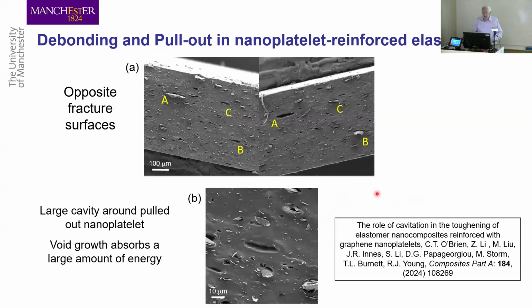And this is the something else that's going on. If you look at the opposite fracture surfaces of one of these torn specimens, you can see that you get holes on one side, and there's the hole, and there's the pulled out flake. There's a pulled out flake, there's a hole. There's a pulled out flake over there, and there's a hole. But what's interesting is these holes are enormous. They're much bigger than the thickness of the flake. And what's happened in this case is you've got massive void growth around where the graphene was. The graphene is causing voiding to take place, and voiding in rubbers absorbs an enormous amount of energy.